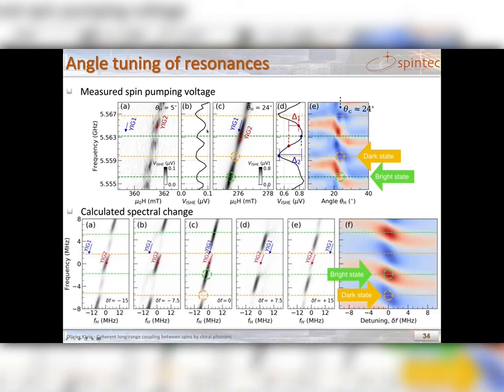Our calculation can reproduce most of these features using this triple coupled equation. At zero detuning, you can see the formation of bright and dark states. Also the contrast inverts at the crossing point. Finally, we can reproduce in this color plot exactly the same things that were represented in the data.